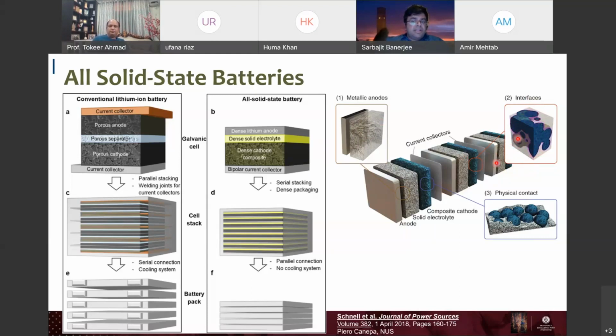And then in a solid electrolyte, lithium is a conversion electrode, right? So lithium is getting into the electrolyte and then depositing out. There are large volume changes involved. How do you maintain physical contact between the solid electrolyte and the cathode, or the solid electrolyte and the anode, across hundreds of cycles? And a lot of this is done by applying pressure that keeps the stack together, right?